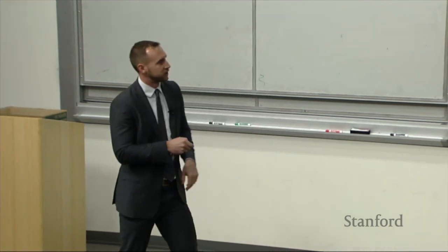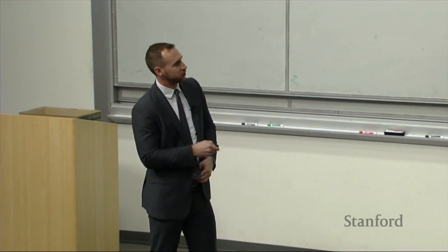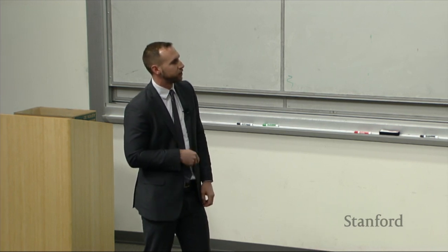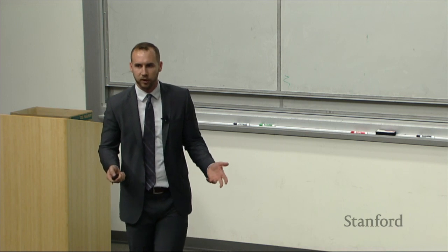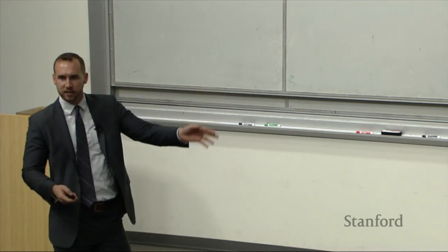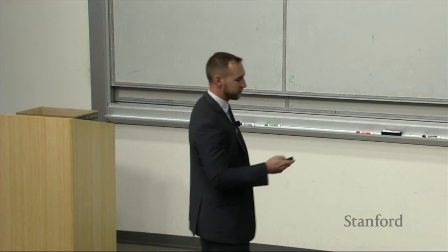And the first thing that we did was we just computed all 20 of these for the 40 materials, and we looked at them one by one just to see, does this one predict conductivity? Does this one predict conductivity? And the correlation coefficients are in this column, and you can see they're all pretty small. They're all less than plus or minus 0.3. So of our initial 20 guesses, none of them really were good predictors.